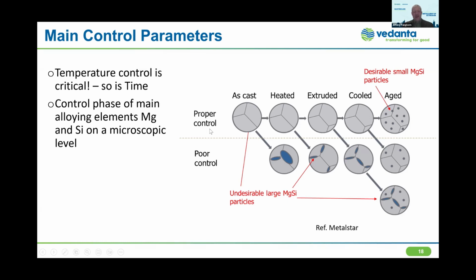And here's a schematic showing a proper control. Of course, you're getting excellent billet here with minimal Mg2Si, which is really a result of their homogenizing process and the way they cool. There might be some, but it won't be anything that you can't handle. As you heat, you really won't have any significant growth. You're not having any major delays where you're staying at an elevated temperature for a long time, getting it through the preheating process. You're extruding at a sufficiently high temperature to solutionize everything. You're cooling at a rate that maintains all the mag and silicon in solution. And then when you age, we get these finely distributed particles that are optimum for strength.